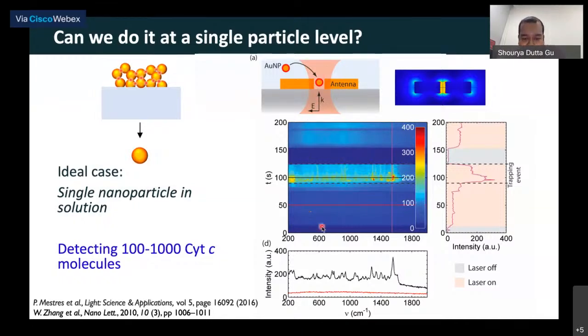So here what we are doing is initially the laser is off, then we turn it on at this point at a low power, but we still don't have any trapping. However, at this point, we actually increase the power so that it's enough to hold these single particles. And what we see is after a certain time, after we increase the laser power, we start seeing these Raman peaks appearing in this spectrum. Again, after a certain time, when we think we have enough spectrum, we stop the laser and we let the particle move out.